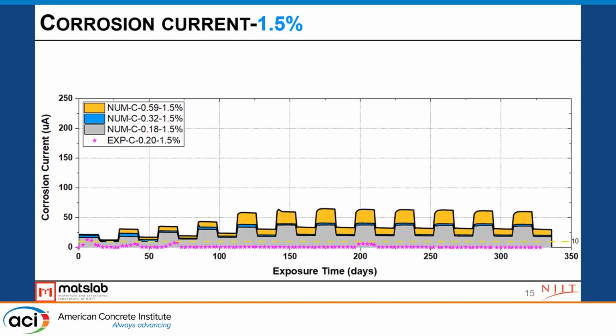We see jumping up and down of this result because we applied wetting and drying cycles. So when we add the solution, the corrosion current is higher. When we remove the solution, it drops down. And the scattered data here is the test result. Actually, we didn't see much corrosion from the test. It is possibly because of self-healing of the concrete, or just because of the variability of the test result. We have a limited number of specimens tested.